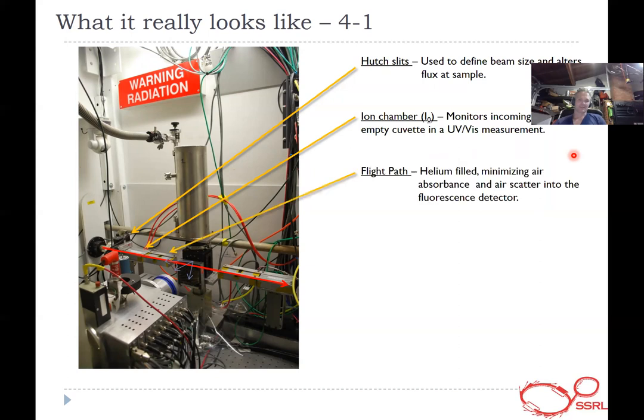It's before the sample. Here at 4.1, we have a flight path, and that's just to get the beam to the sample with minimum air scatter and minimum air absorbance. So you get higher quality signal, more flux at the sample with less air scatter into your fluorescence detector. A sample holder of some sort, in this case, it's an LN2 cryostat. And we'll go over a lot of the different types of sample environments we have at SSRL available for you.